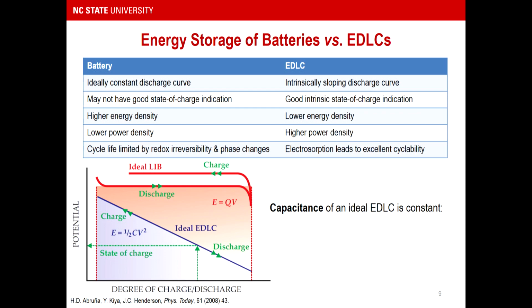Something else to notice from this curve is that because batteries undergo physical and chemical changes, there is a hysteresis between their discharge and charge that grows larger and larger as we go to higher currents. In the case of double-layer capacitors, these mechanisms are not present, so you can get nearly ideal reversibility, and that's why these arrows are drawn on the same line. And so when you go to very high power densities, that energy efficiency is very, very high. And that results in also very high reliability, excellent cyclability with the 100,000s or millions of cycles that are afforded.